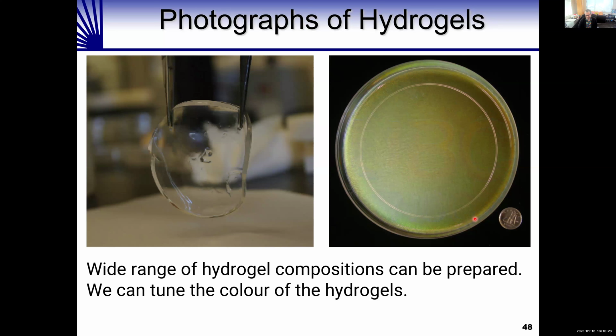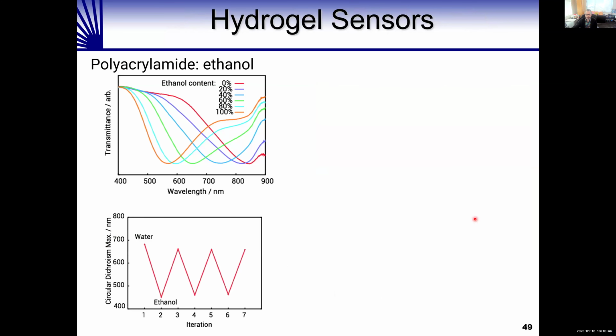Now, as I mentioned, hydrogels swell in water, but they don't swell in alcohol or ethanol. So what we explored was using these as sensors for detecting the concentration of ethanol in water. If you take the hydrogel, initially it reflects light around 550 nanometers - these are the reflection spectra for the samples.